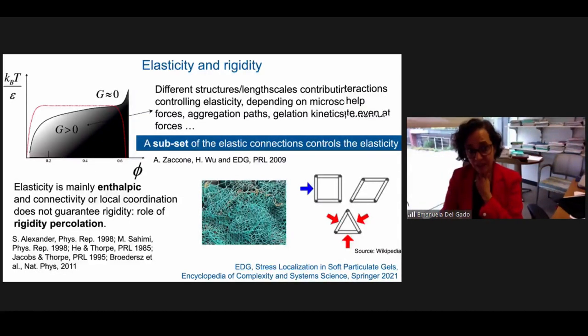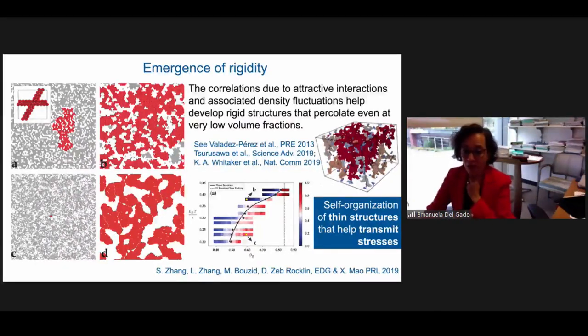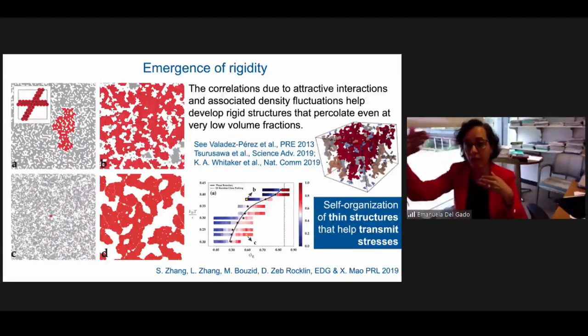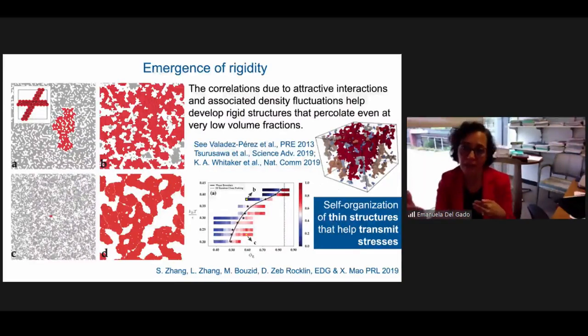So we've studied these issues in this system with Xiaoming Mao and Zeb Rocklin a couple of years ago, where we were pursuing this idea that the emergence of rigidity in the system should be looked at as a rigidity percolation problem. So where you start first to build these local rigid structures, which then connect into a spanning percolating network. But this is not quite the same rigidity percolation that has already been studied a lot, in general, for disordered materials, where you consider that these structures are going to be connected sort of randomly because of the disorder of the system.